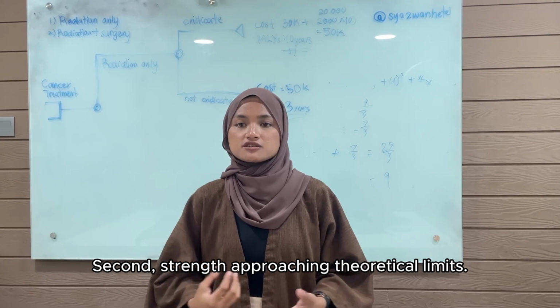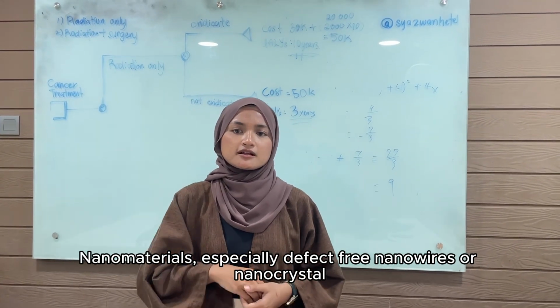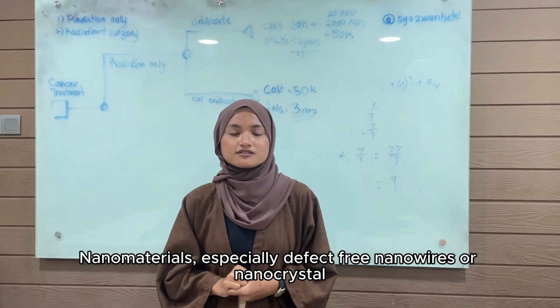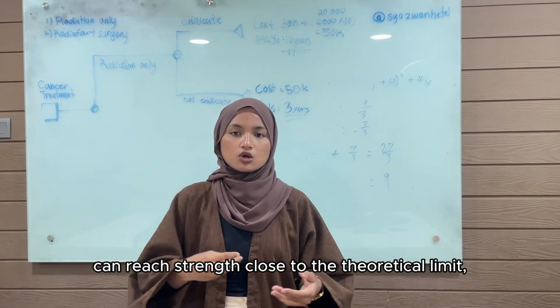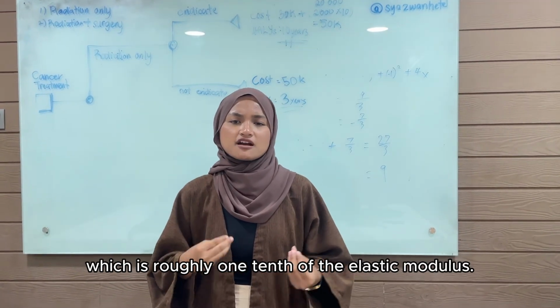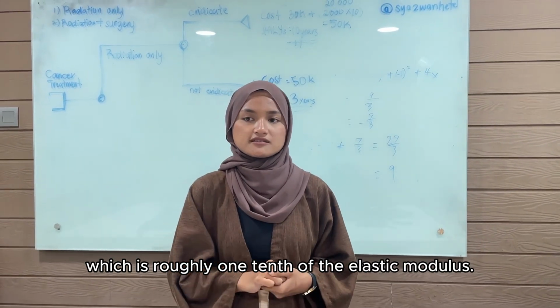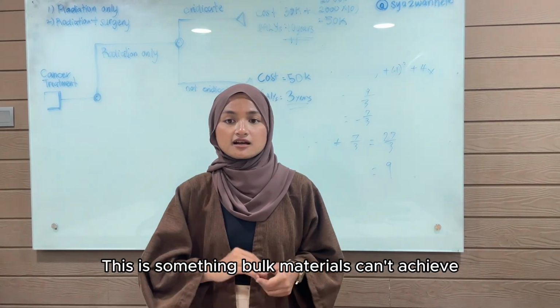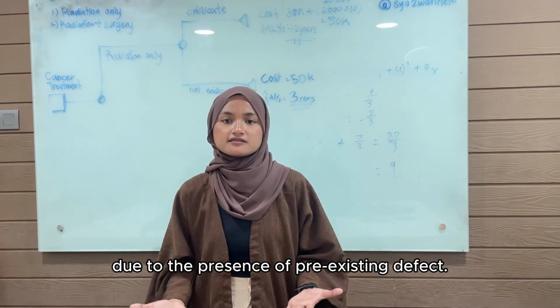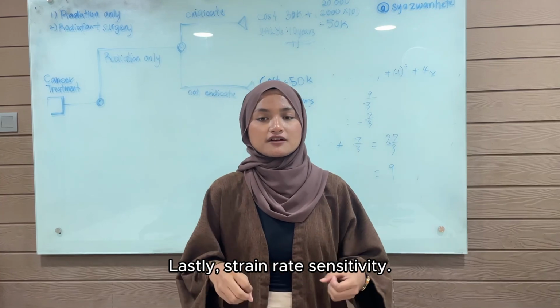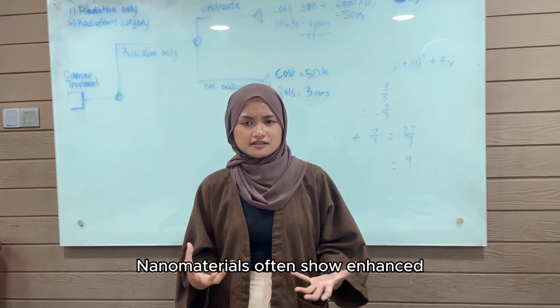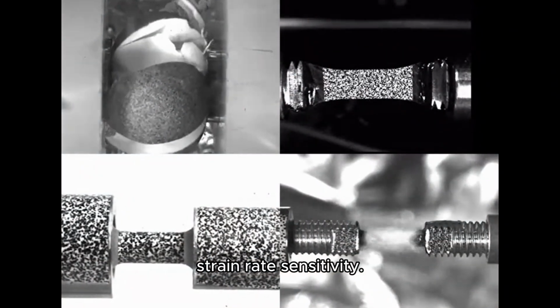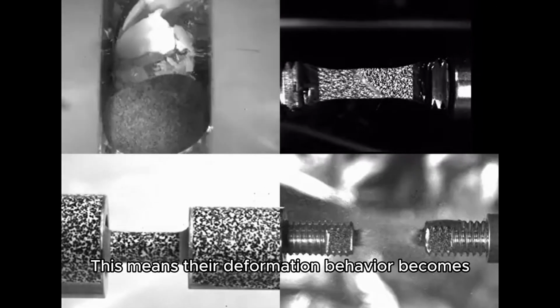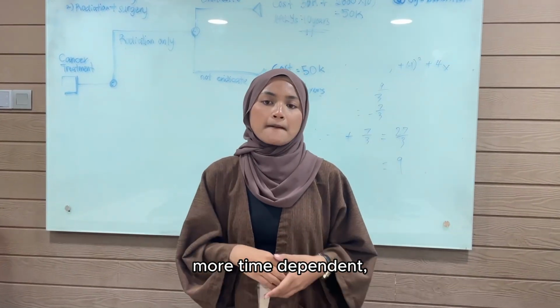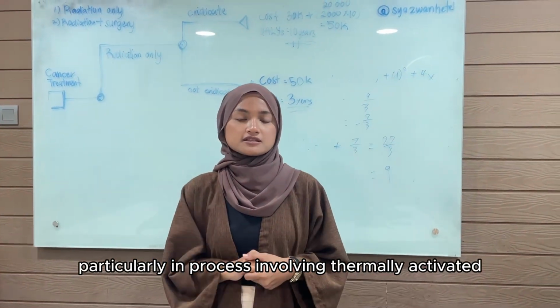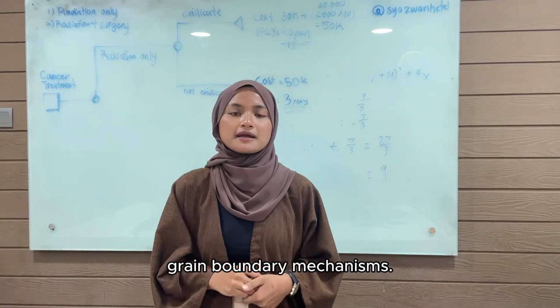Second, strength approaching theoretical limits. Nanomaterials, especially defect-free nanowires or nanocrystals, can reach strength close to the theoretical limit, which is roughly 1/10 of the elastic modulus. This is something bulk materials can't achieve due to the presence of pre-existing defects. Lastly, strain rate sensitivity. Nanomaterials often show enhanced strain rate sensitivity. This means their deformation behavior becomes more time-dependent, particularly in processes involving thermally activated grain boundary mechanisms.